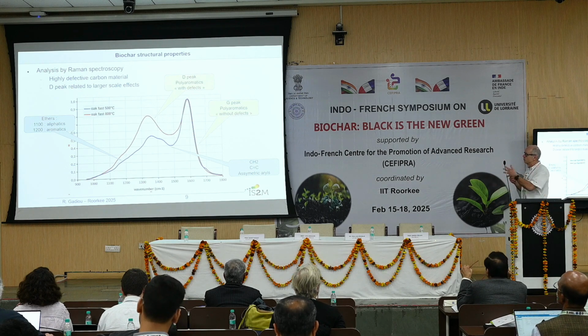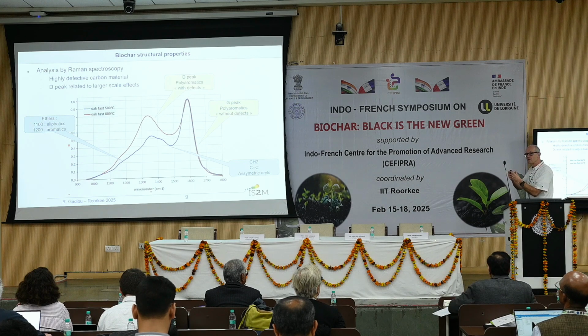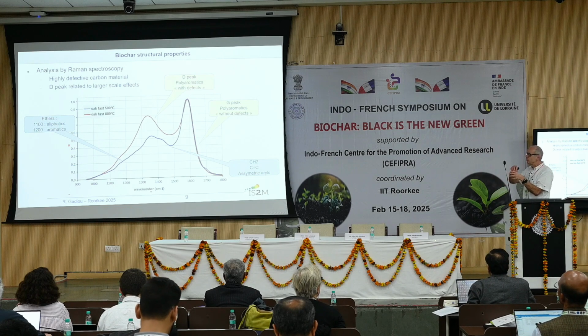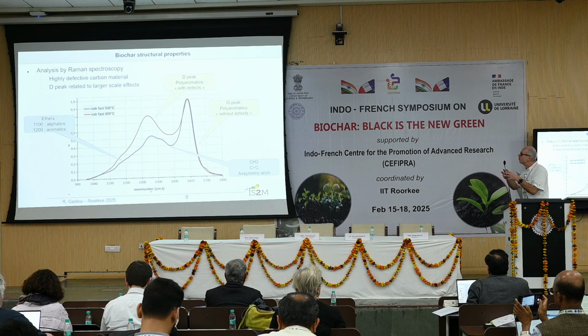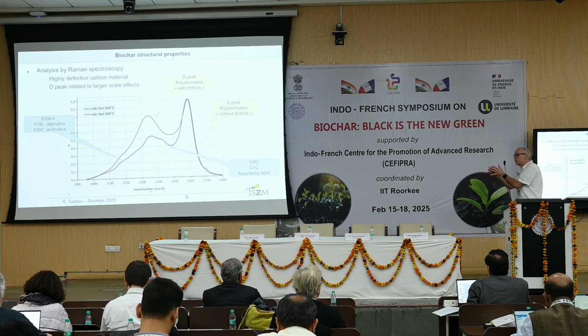since from the theory, from what, for example, Andrea Ferrari has shown, what we call defect for Raman, for the D peak especially, is some kind of density of defect on a given surface. And this gives access to some nanometer scale, which is not possible to obtain by NMR or by X-ray diffraction. This is very interesting. So the D peak shows that you have a graphene with a density of defect which is relatively low, but at the scale of 1 nanometer, 2 nanometer.